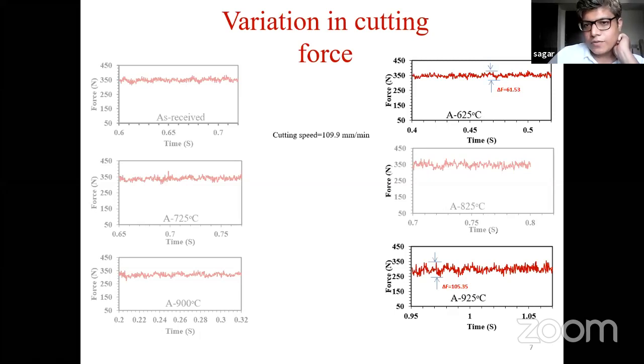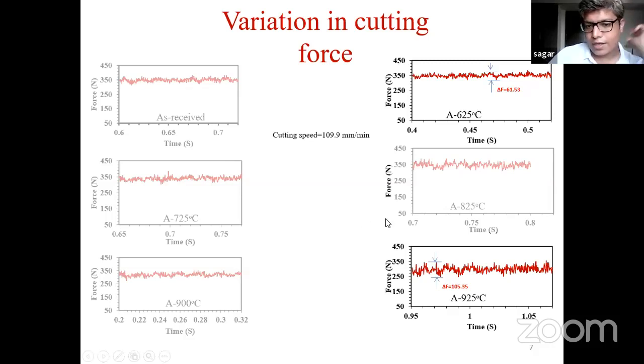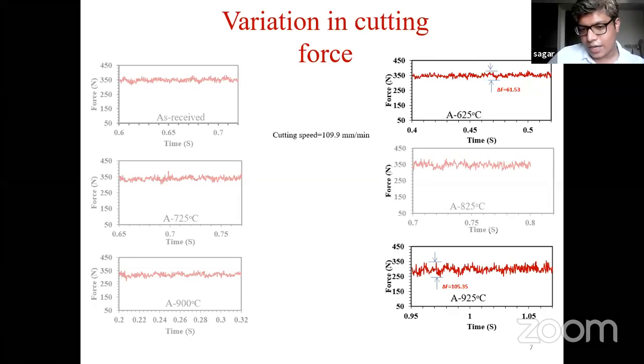So why is this cutting force variation happening? Just as we have seen earlier, because of the segmented chip formation. This means that if you have a higher grain size sample, the segment variation will be huge. That means between maximum and minimum forces, there will be a huge variation, which could affect the machinability. Although the average cutting force value has lowered in this region, still the variation has increased. Here you could see the average cutting force value is around 300 Newton, whereas here the average cutting force value is around 350 Newton. However, the variation has been reduced a lot.